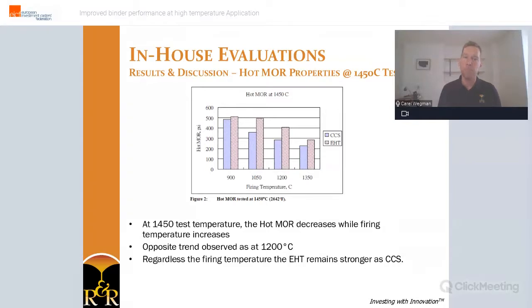Now, this graph provides the same hot MOR data as the previous one, but for the test temperature of 1450 degrees C. And now we actually see the opposite trend as was seen at the test temperature of 1200 degrees C. The hot MOR for both the EHT and CCS binder decreased while we increase the firing temperature. 1450 degrees C is, of course, well above the transition temperature of the glass phase. And the reduction in strength of the shell at this higher firing temperature is because the presence of this liquid glass phase allows the refractory grains to slide over each other, and it's weakening the shell when it's subjected to a load. So a higher firing temperature promotes a more complete glass phase network and therefore an easier grain sliding.